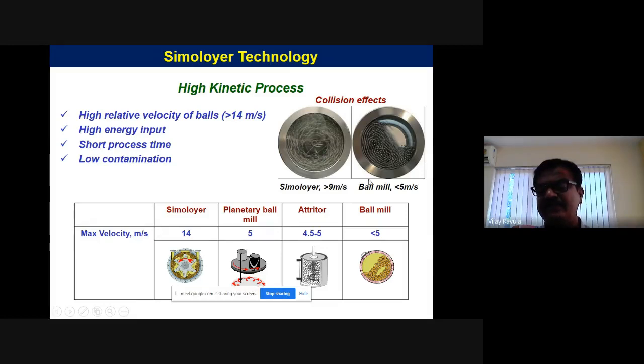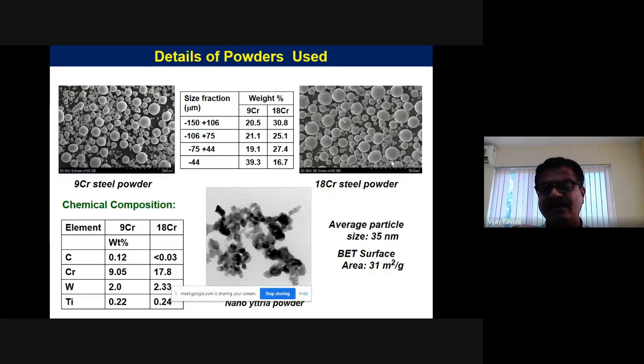And the beauty is, if you look at our mill, there are no dead zones. It is designed such that at any point of time the balls and powders are always in motion. Unlike any ordinary ball mill, where there is always a dead zone and all the ball mass is on one side. So these are all the advantages of this mill, and we made use of it and produced these powders. And these are all the starting powders.